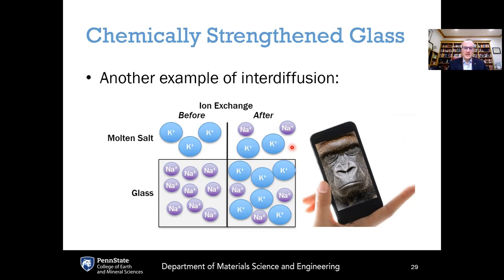An example where the net flux is zero would be the ion exchange process for chemically strengthened glass, such as the Gorilla Glass on your phone. Here, the initial glass is made containing smaller alkali ions, such as sodium. That glass is submerged in a molten salt bath with a larger alkali ion, such as potassium. Over time, the sodium diffuses out of the glass into the salt bath, and it is replaced on a one-for-one basis by potassium, and that is to maintain charge balance.